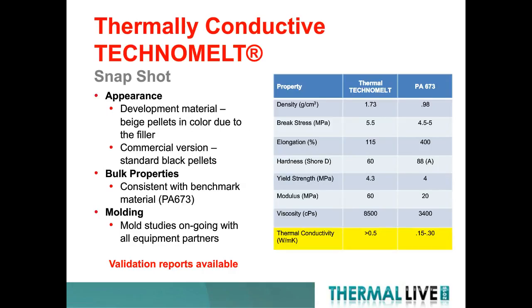Brought a quick snapshot of traditional Technomelt materials versus the thermal materials. You'll notice the density itself is higher, and that's due to the filler addition. The break strength and the elongation properties all maintain well enough to survive the environmental exposure that we would expect to see: thermal cycling, high temperature storage, stress itself.